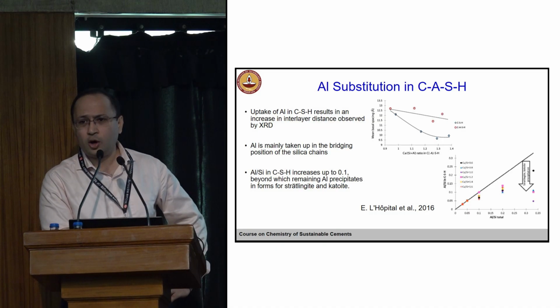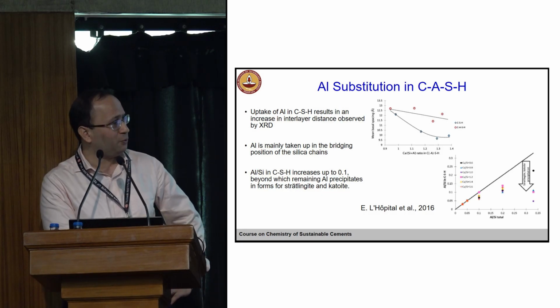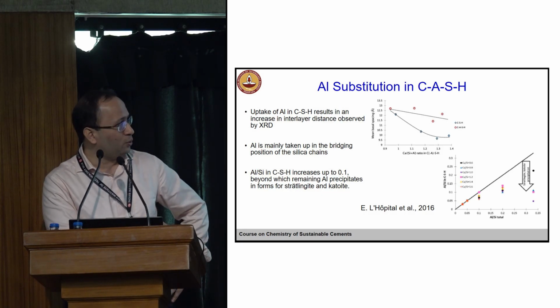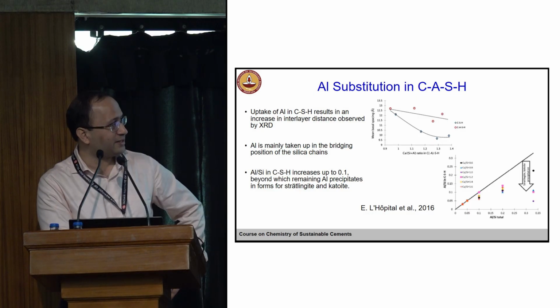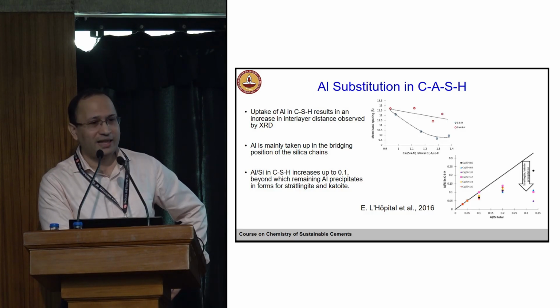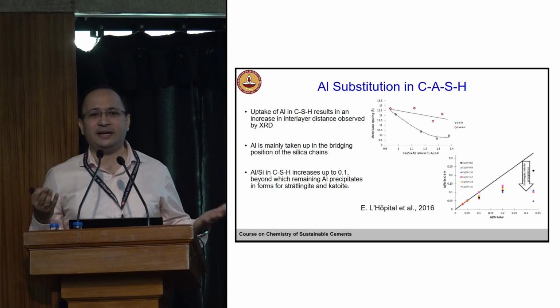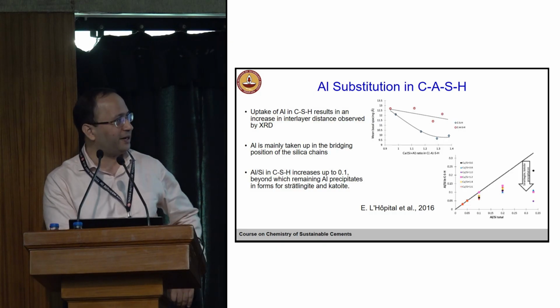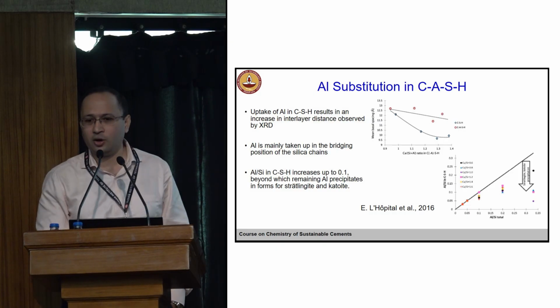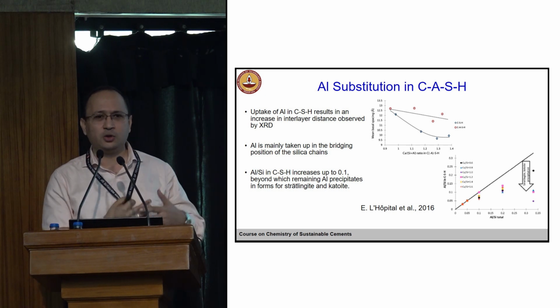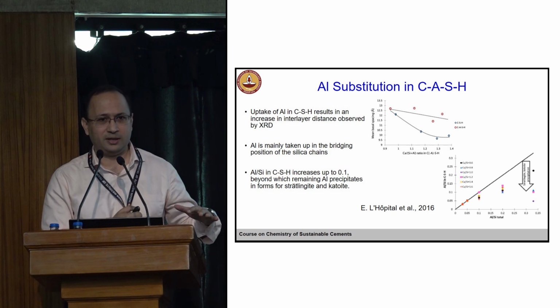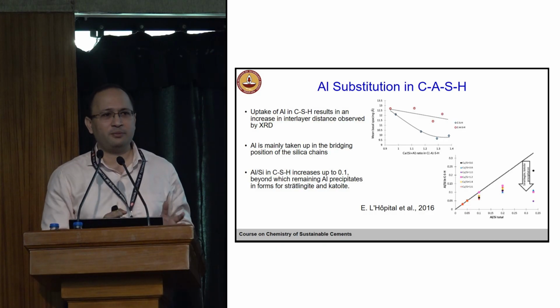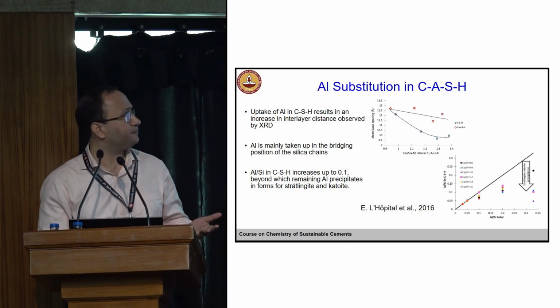But it can only incorporate to a certain level, right? So if you keep adding, let's say in this case up to 0.1 Al to Si ratio, it was fine. But beyond that, if you add more, then it will precipitate. That extra alumina will precipitate either in the form of strätlingite or a katoite phase. So CSH can only uptake to a certain extent. Beyond that, you have alumina bearing phases which will get precipitated.